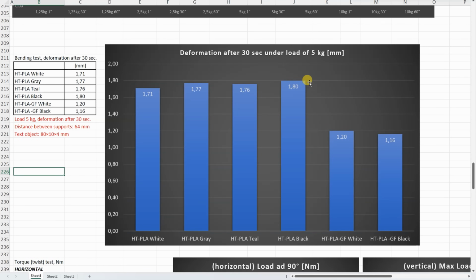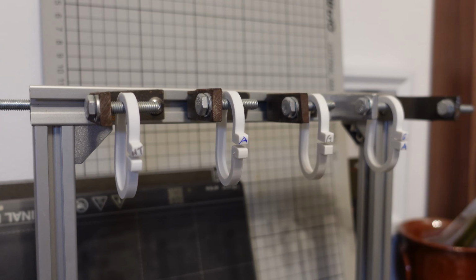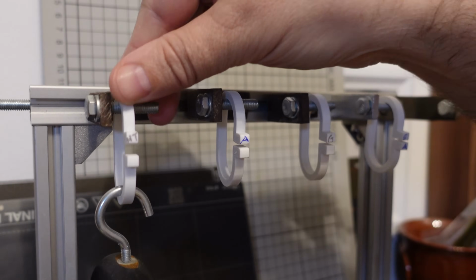HT-PLA, very similar deformation between the colors, and the glass fiber version again very similar between the colors and less deformation compared to the non-reinforced version, which is typical for these materials. Creep test, the deformation under the constant load.